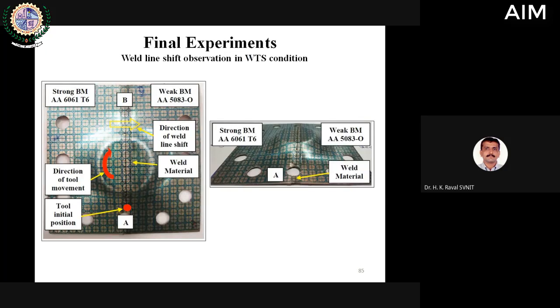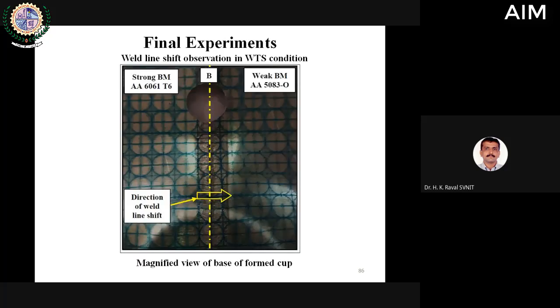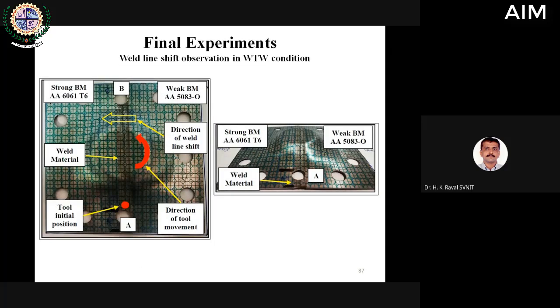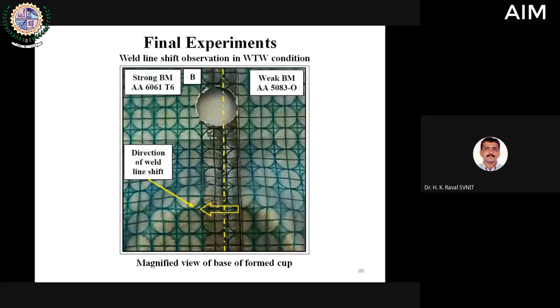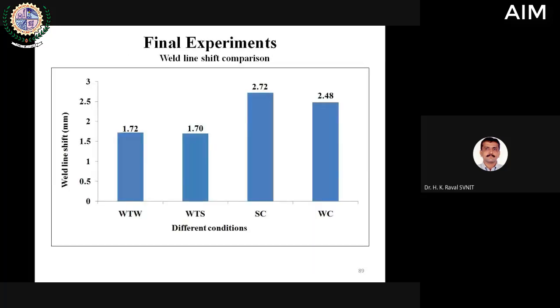You can make out the starting positions on the rail. In the earlier case, the starting position was on either the weak material or the strong material. This is WTS, this is WTW, fine. And then the weld line shift was compared, and it is observed that the weld line shift is found to be minimum in the WTS condition. Next minimum is WTW, meaning weld to strong and weld to weak give the minimum weld line shift compared to the strong center and weak center.